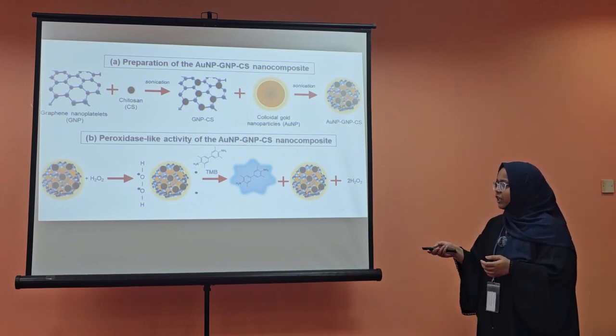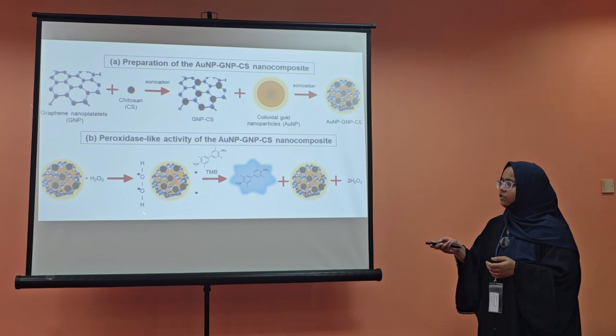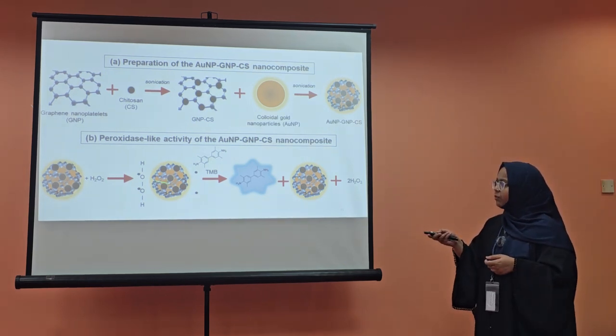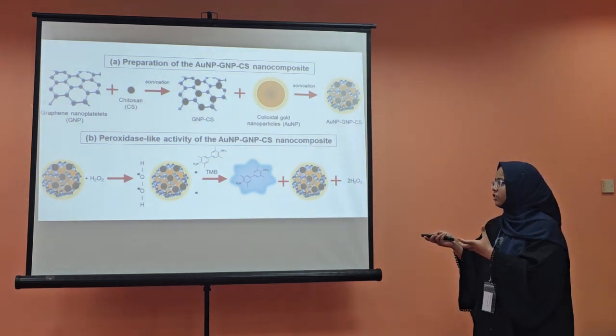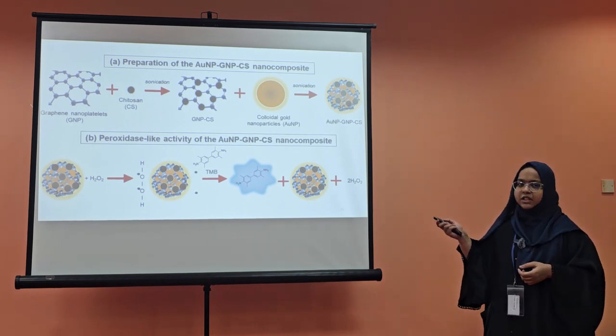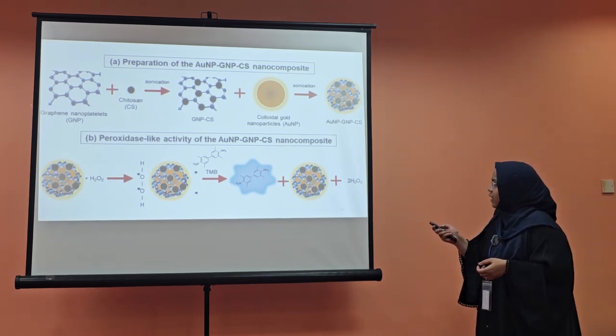In the presence of nanozyme, the hydrogen peroxide is dissociated to give free hydroxyl radicals, which then oxidize the TMB to give a highly blue-colored solution. The immediate color change confirmed the peroxidase-mimicking activity of the nanozyme.